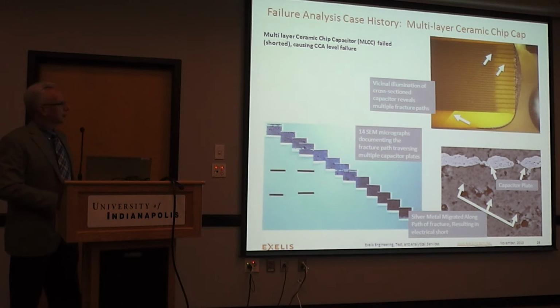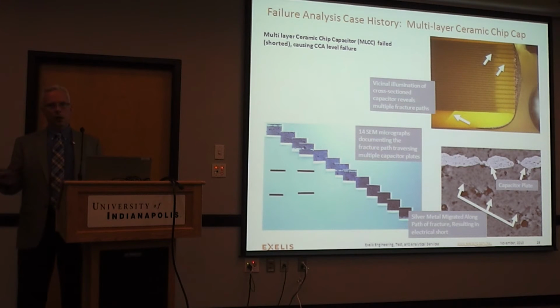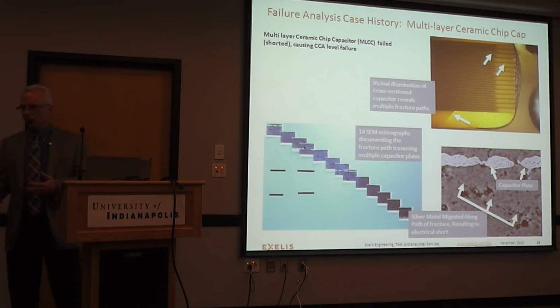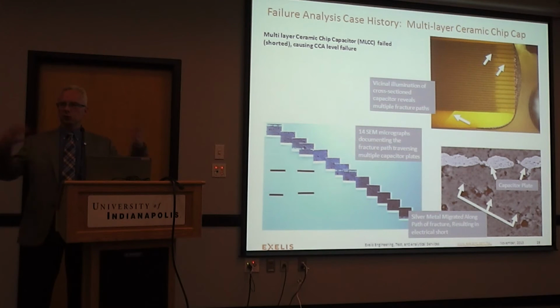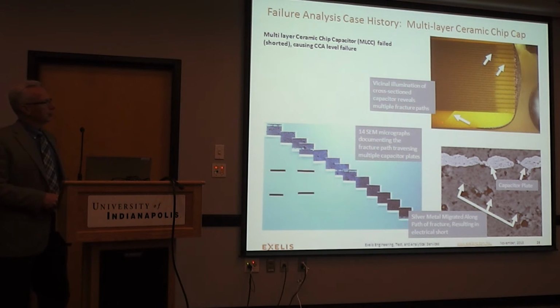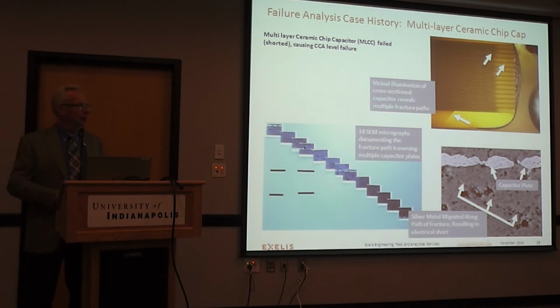But the history here is that a chip capacitor that was in a larger assembly shorted out during a circuit level test. And this was on a program in which every failure would be scrutinized in detail. The customer had a lot of visibility in here. It went into a system that really needed to be a high reliability system. And so when we identified a fracture that traversed multiple interdigitated anode-cathode plates, that told us that we pretty much had identified the mechanism. That told us right away that the chip cap had fractured.